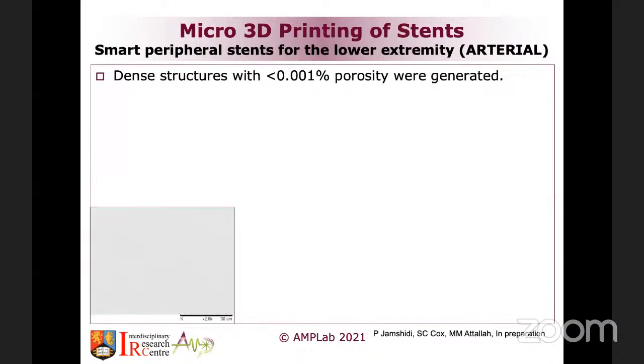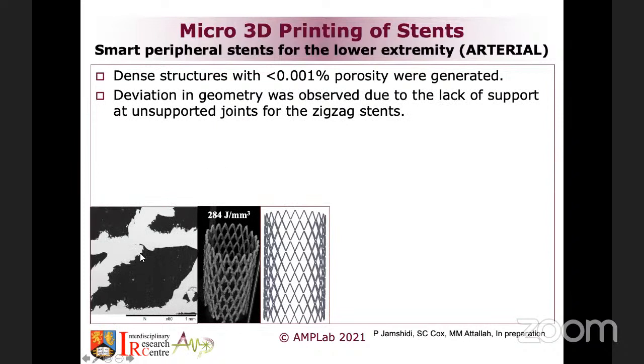So we did a lot of studies to look into their printing, using a process called laser powder bed for printing of metals from metal powders. And as you can see, you don't see any defects inside. They are all entirely solid and clean. Unfortunately, the surface is not that uniform, and that's because the metal powders that are used for printing may stick sometimes to each other, generating a slightly ugly kind of shape. But that depends on the geometry you are printing.